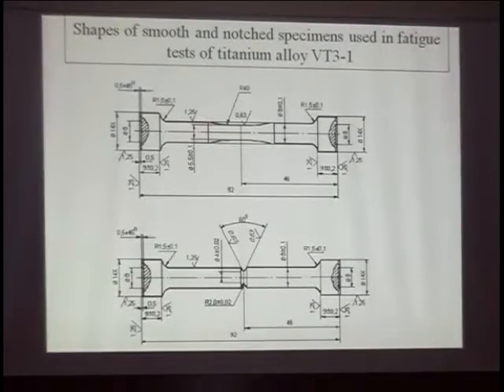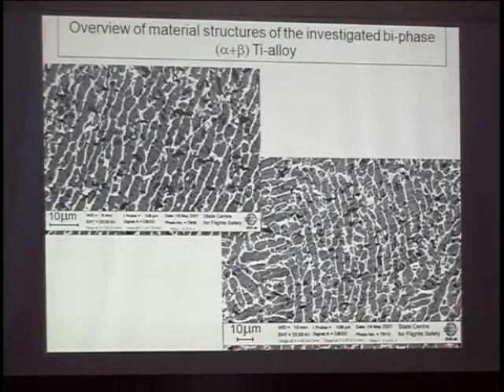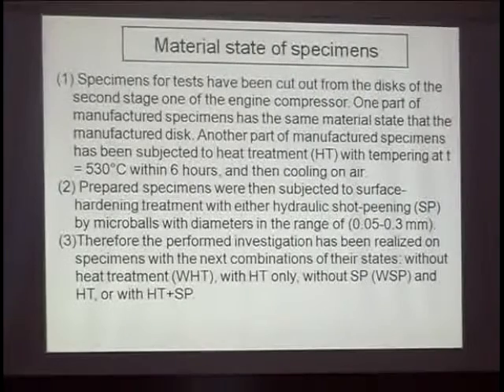Two types of specimens were used, named smooth specimens and notched specimens. There can be seen shape parameters. This is a well-known type of alpha-beta titanium alloy with mixed lamellar and globular structures. This slide presents information about different types of heating, shot peening of the surface slightly, and different states of material: with heat treatment, without heat treatment, with a combination of heat treatment and shot peening, without shot peening, notched and smooth specimens. All these combinations were investigated to see if it will be the same manner of subsurface material cracking that was announced on the previous slides.